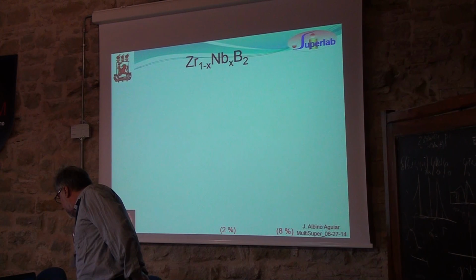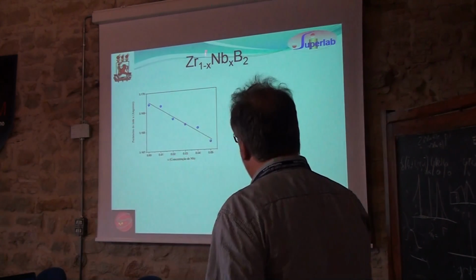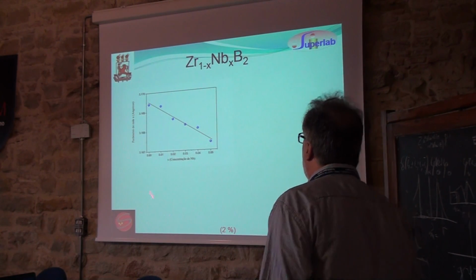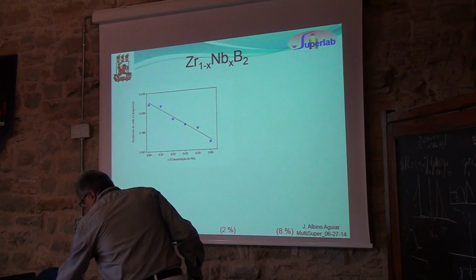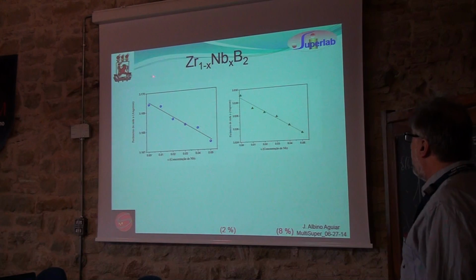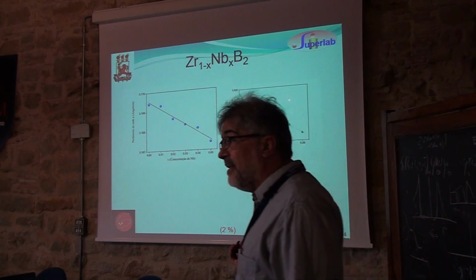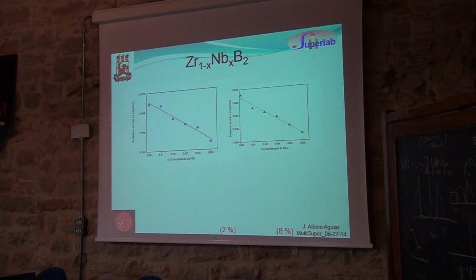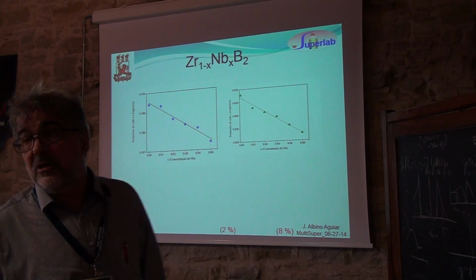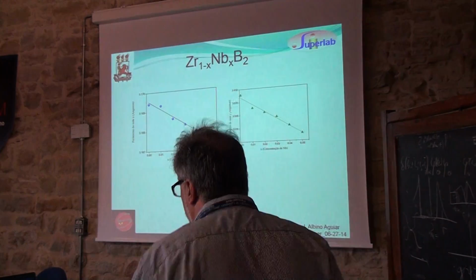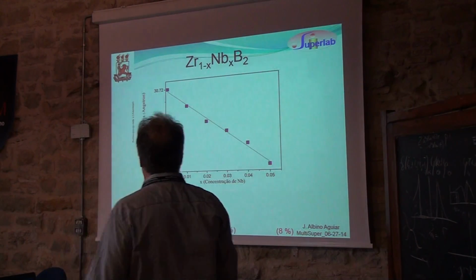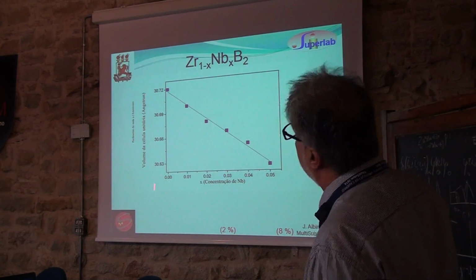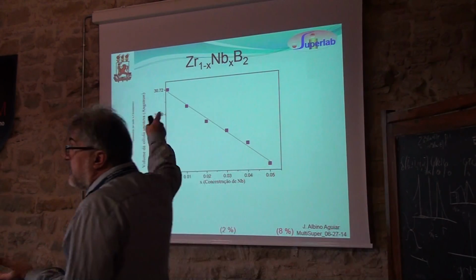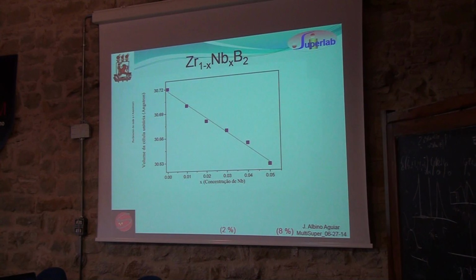So we can get the a parameter as a function of dopant concentration, and it decreases linearly. Also the c parameter. You see that it's different from the vanadium one. In the vanadium case, the a parameter stays constant with the doping concentration, and the c decreases, and you have a solubility limit. Here, as far as this concentration, we have no solubility limit. But if you put these two together, you indeed have a decrease of the unit cell. We have compression. In the case of vanadium, we have a c compression, but here the whole cell is compressed.